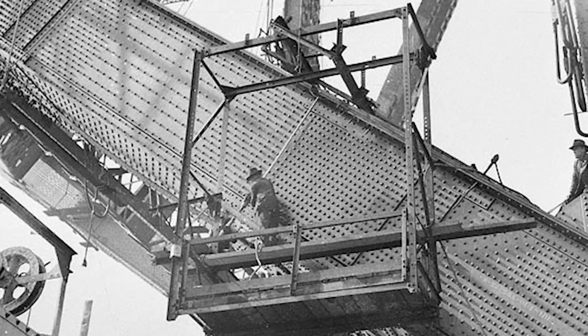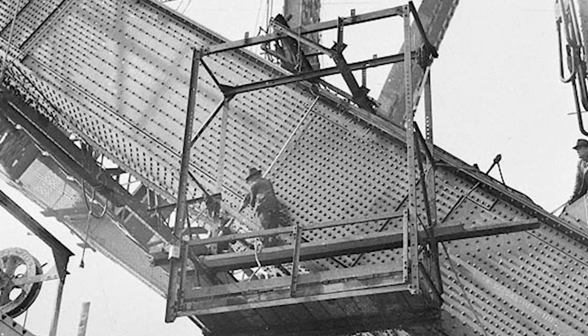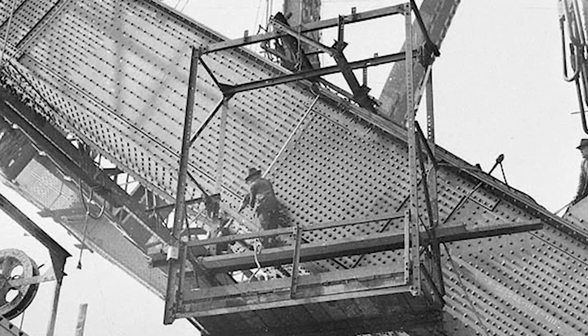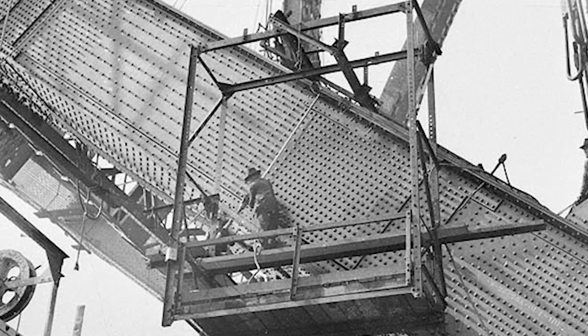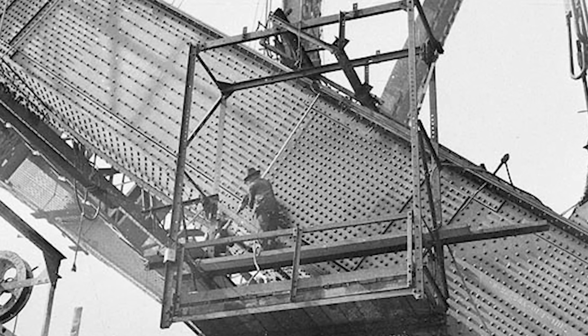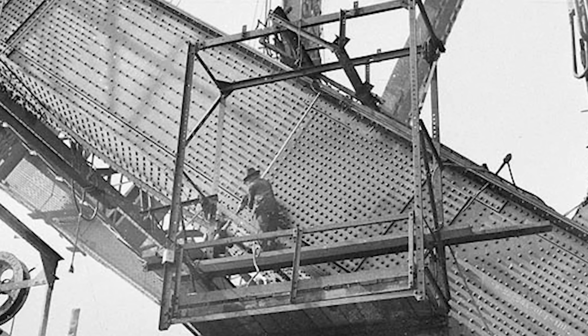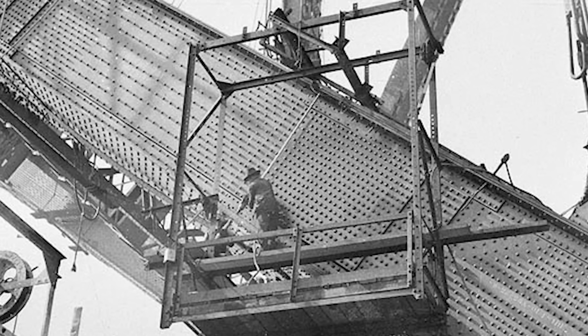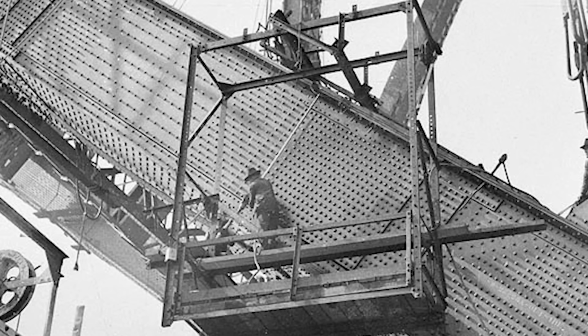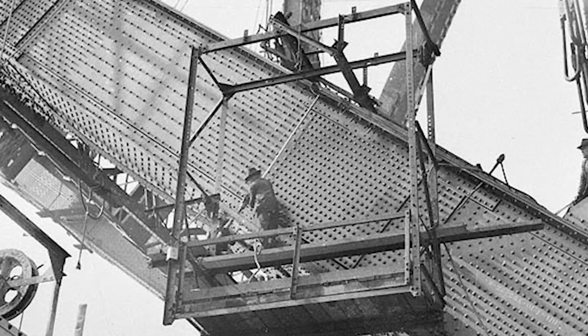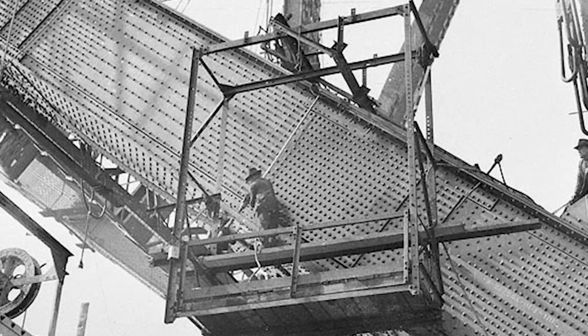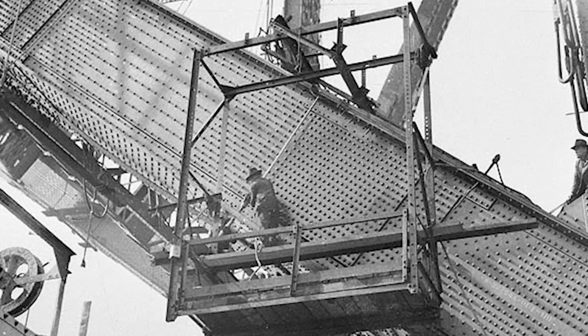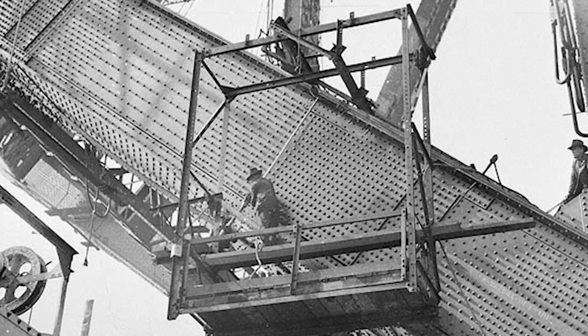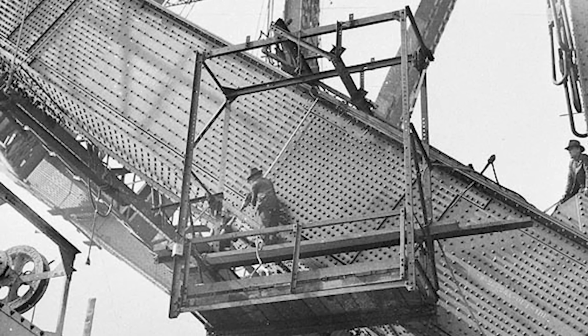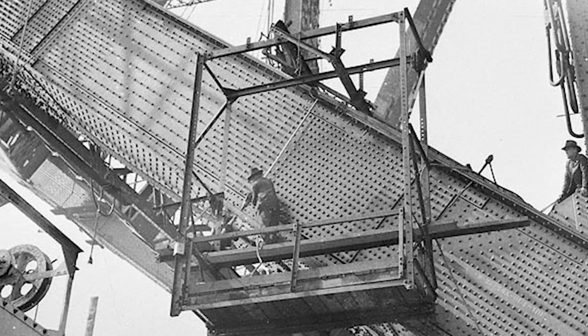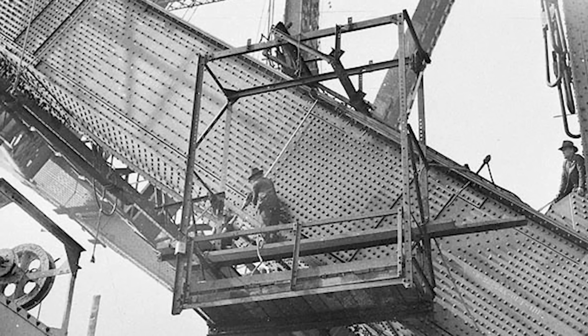Toretti had lost his left eye to flying steel on the Hellgate Bridge in 1916, but his remaining vision had developed supernatural accuracy. He could judge the trajectory of a thrown rivet in variable wind conditions, positioning his cone to catch the white-hot fastener without letting it cool below optimal driving temperature. The margin for error was measured in seconds. A rivet that cooled below 1600 degrees wouldn't fill the hole completely, creating loose connections that would fail inspection and require drilling out for replacement.